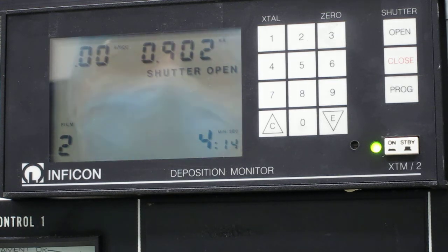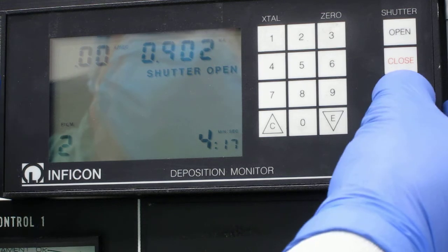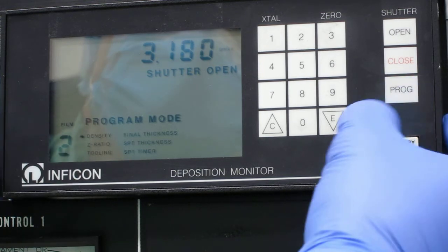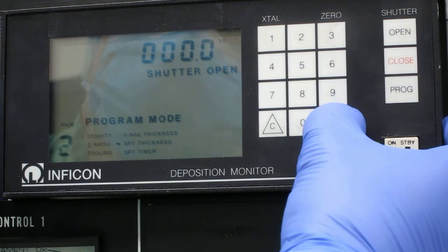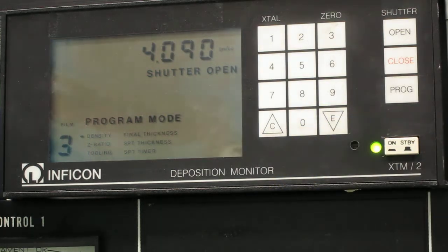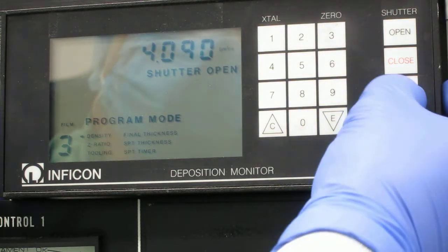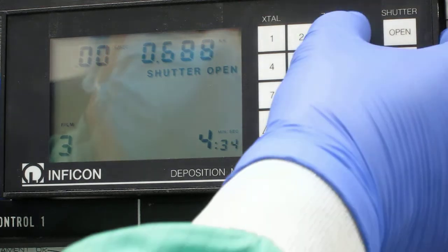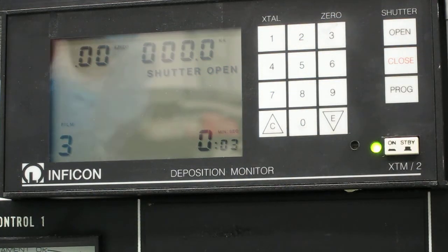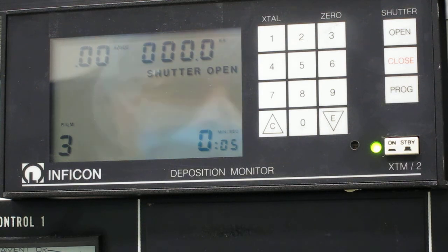Our second deposition layer can now begin by first selecting the film number that corresponds with the crucible we're using. In this case, film number 3, which corresponds to ZnS. As usual, we'll zero the meter just before we deposit that layer. Deposition now occurs the exact same way as the previous layer, by increasing the emission current gradually, opening the shutter, controlling the rate using that emission current, and then closing the shutter to stop the deposition.